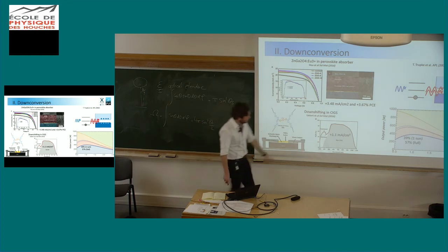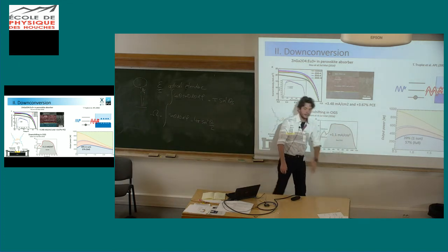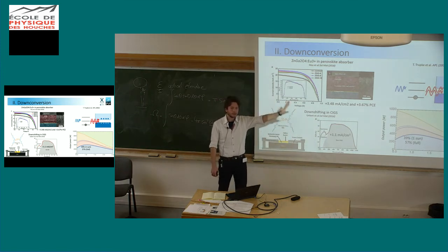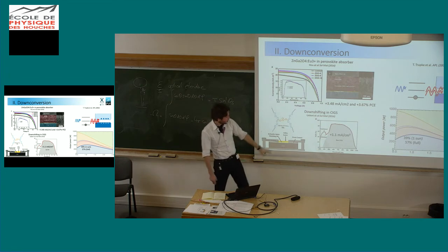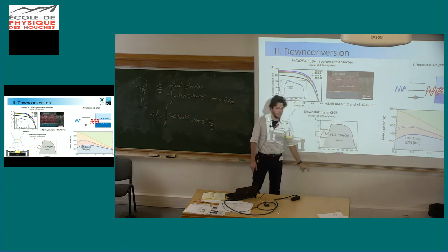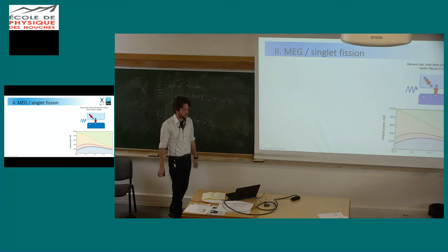And you see that this here was the EQE for bare CIGS. And by transforming blue photons into red photons, not even making down conversion, but just making downshifting, you could increase significantly what was collected here for high energy photons. Okay, two more to go.